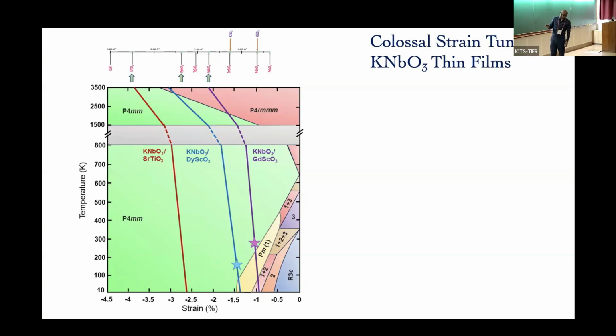But the other thing is, when you heat this, at some point it loses the ferroelectricity and becomes paraelectric. It's no longer electrically polar, the centers of positive and negative charge are not separated. That phase transition, you see, has moved from here up, and then we had a break here because it's such a long diagram, and then it's going over here. These are 1,000, 2,000, 3,000 degrees Kelvin. The typical transition in potassium niobate is about 420 C, which is about 700 Kelvin. Now just a little squeeze, and that transition has gone to 2,000-3,000 Kelvin, well beyond its melting point.